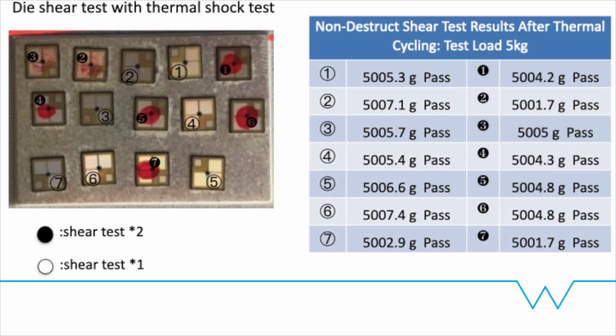So in this figure, the numbers with black background mark the 7 chips that went through the shear test twice, before and after thermocycling. And the numbers with transparent background mark chips that only went through the shear test after thermocycling. One thing I need to mention here is that this time what we did is a non-destructive shear test. And the test load is set to be 5 kilograms, which is the minimum requirement. So non-destructive shear test means you push a die, and when you reach 5 kilograms, you keep the force for a few seconds, maybe 5 seconds. And if the die is still attached on the DBC board, it passed.